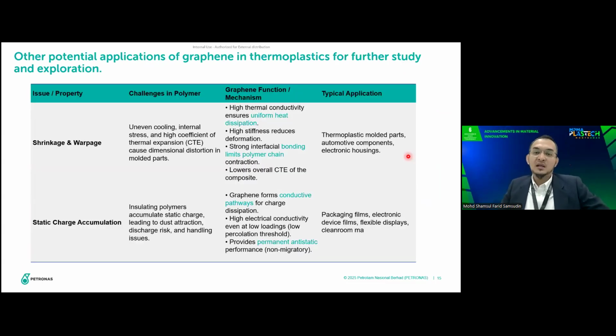And we can see there are other potential applications of graphene, not only to improve mechanical, barrier, thermal, and also UV properties. It can also be further explored to see how graphene can improve the shrinkage and warpage issue in thermoplastic molded products, as well as for anti-static applications, because we believe that graphene with a very minimum loading can give very good heat dissipation, and it can uniformly distribute in the polymer. And graphene particles can also give good interfacial interaction with the polymer, and it will hold the movement of the polymer chain and maintain the dimension of the molded product.